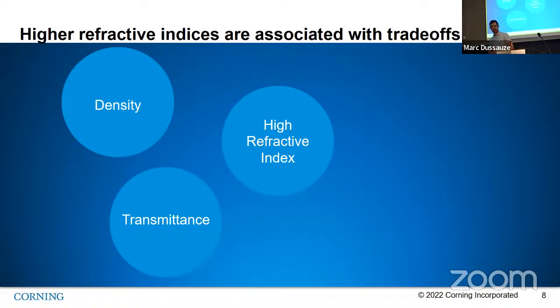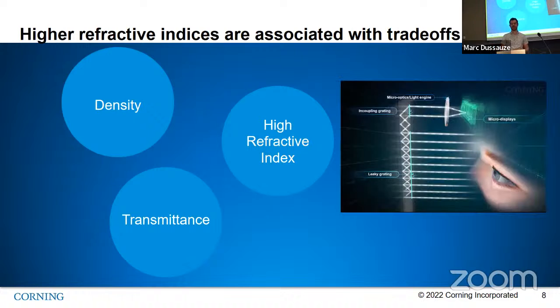We have another requirement, which is transmittance, because as I told you, we're sending light in red, green, and blue. Red and green, we don't have any issue. All of our glasses are fairly transparent in those wavelength regions. The blue is really the difficulty for us, because as we increase the refractive index, we tend to shift the UV edge toward the visible. So we're going to be lowering the transmittance in the blue. And we can't afford to do that, because the optical path is actually quite long. It's around a few centimeters long.